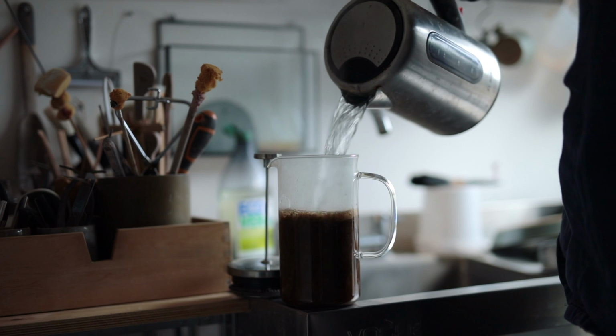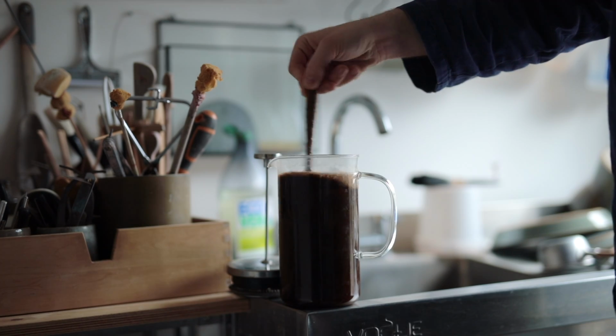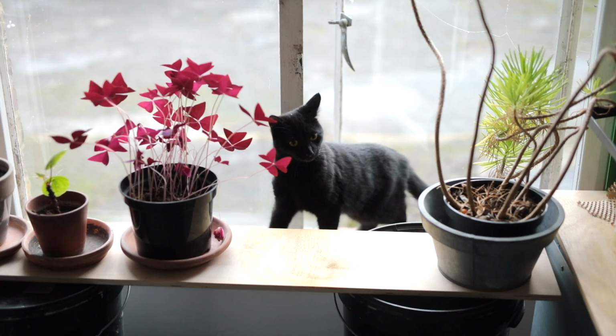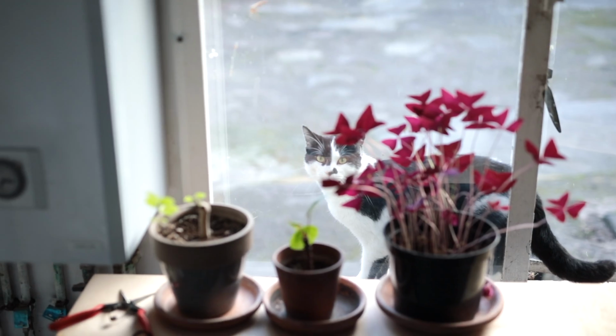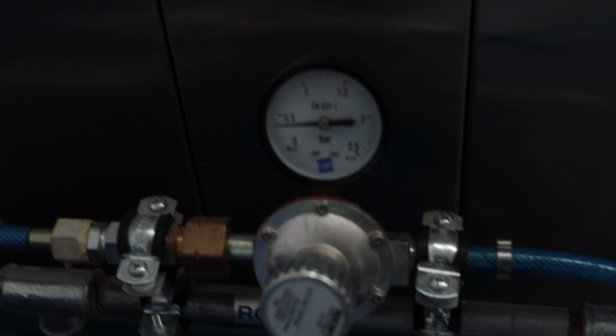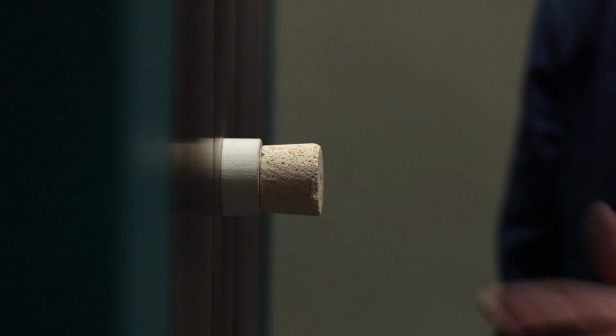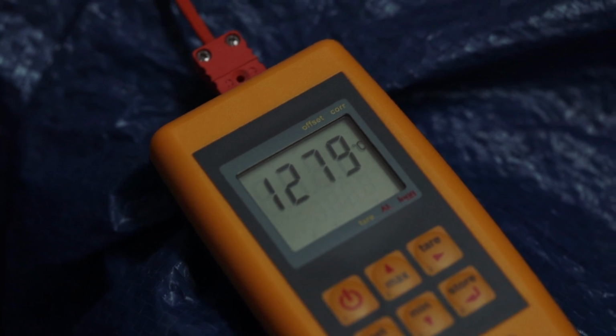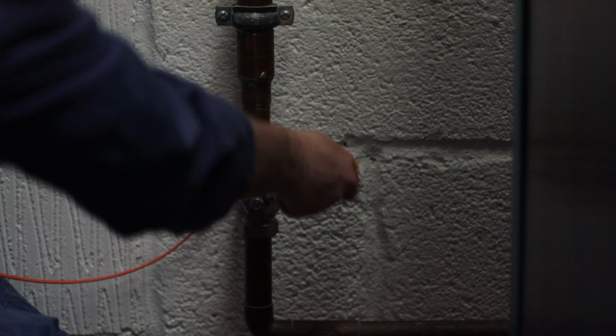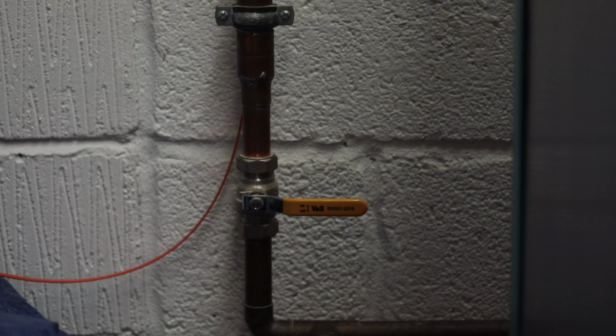I begin my gas reduction firings at 7 o'clock in the morning. The kiln is lit, and for the first couple of hours the temperature is increased very gradually. Then, at 860 degrees Celsius, the reduction atmosphere is initiated by increasing the gas pressure, the air pressure, and by sliding the dampers over the flues at the back of the kiln. Then, at about 1280 degrees, or when cone 10 inside the kiln is fully bent over, about 8.5 hours after starting, the gas kiln will be switched off and quickly crash cooled back down to 1000 degrees Celsius, before being sealed up properly and allowed to cool much more slowly for the next 36 hours or so.